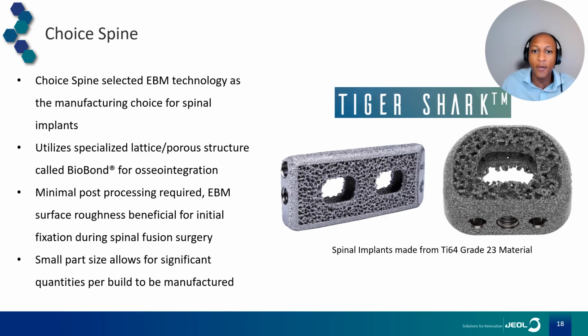The nice thing about electron beam powder bed fusion is, again, the roughness allows for very good initial fixation during the spinal fusion surgery and allows for better bone ingrowth, but also better and more efficient patient outcomes after the surgery has been completed. In addition, because electron beam powder bed fusion can build parts and stack them on top of each other, it really is an optimal technology for spinal implants because you can fit a significant number of parts in one single build, allowing for fast build rates and a large number of parts to come out build to build.